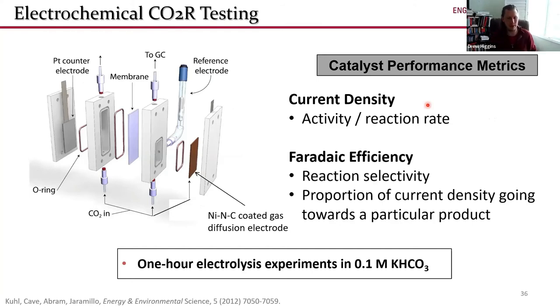And just quickly before we dive into some catalyst performance evaluation, I just want to talk quickly about nomenclature. So you're going to see me talk about current density, which is essentially a quantitative gauge of the activity or the reaction rate of that catalyst towards a particular reaction. So high current density towards carbon monoxide means that the activity is very high for converting CO2 into carbon monoxide. And then Faradaic efficiency, that term is essentially a quantitative gauge of the reaction selectivity. So ideally, we want a Faradaic efficiency of 100%. That means that we have 100% selectivity converting CO2 into carbon monoxide.